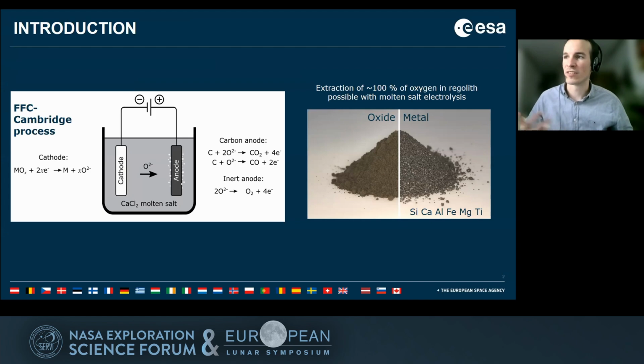So then you will have your oxygen traveling to your anode, as CO or CO2 if you have a carbon anode. But of course, on the moon, if you are interested in the oxygen, you will use an inert anode to recover your oxygen as O2. So far, that's the only process that has shown, to our knowledge, the possibility to extract 100%. So the totality of the 40 to 45 weight percent of the regolith that is oxygen. This process has shown that you can extract all of it. So you end up with a byproduct, a metal powder.